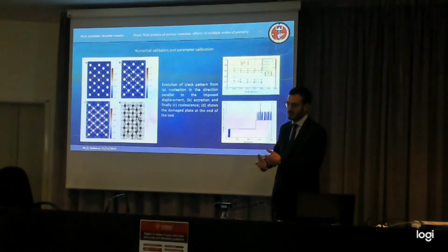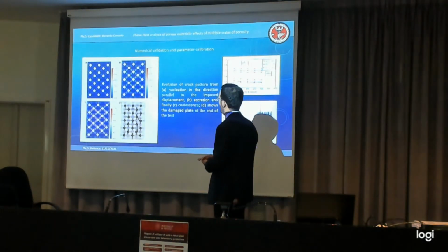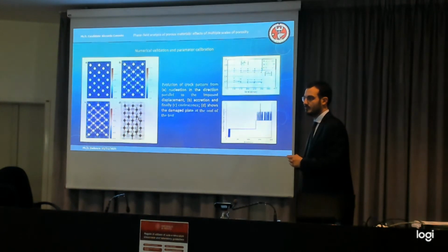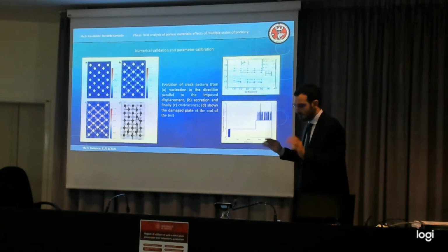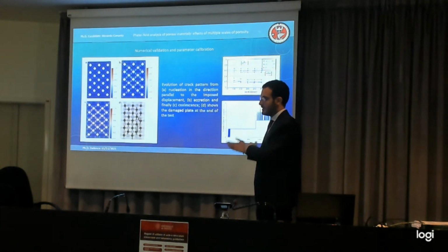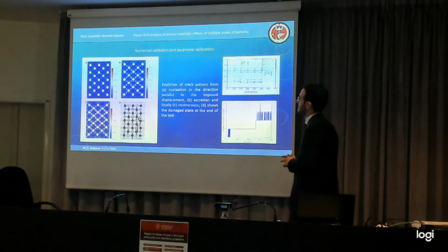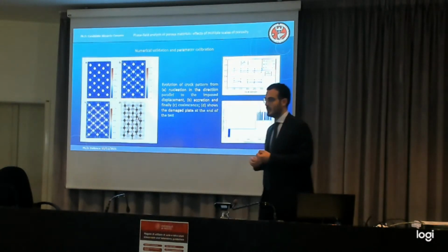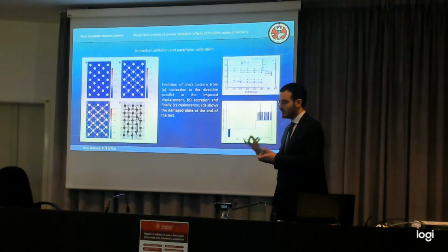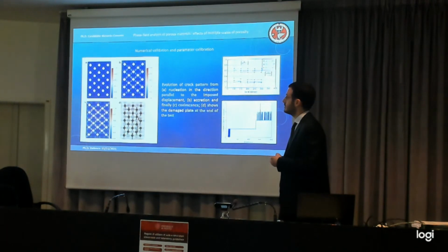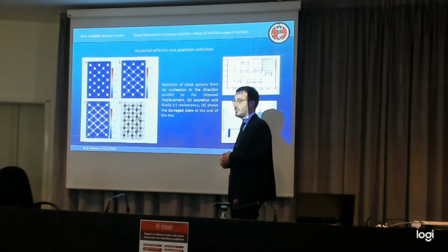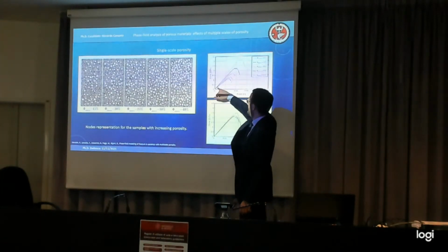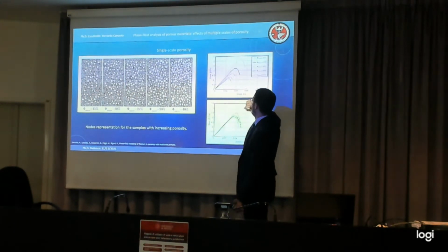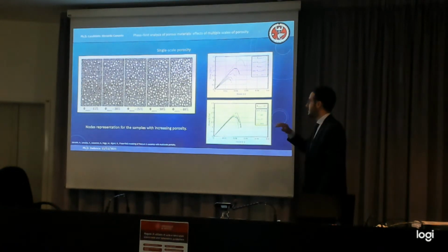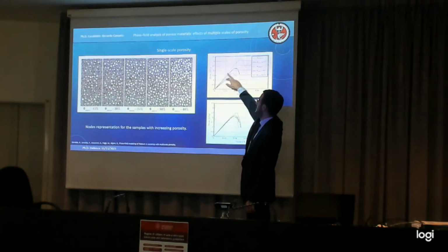Obviously, the elastic part is very easy to calibrate, since before fracture you already determine lambda and mu and the domain parameters. That's it. And then you are left with L and G_c, the fracture and the regularization parameter. Now, these 2 parameters affect the maximum strength of your model, which is the maximum tension that the model will show, and it affects also the total absorbed energy. If I show you, it's the area beneath these curves over here. It's G_c and L. They both are calibrated in this sense. So you have your curve, and then you just